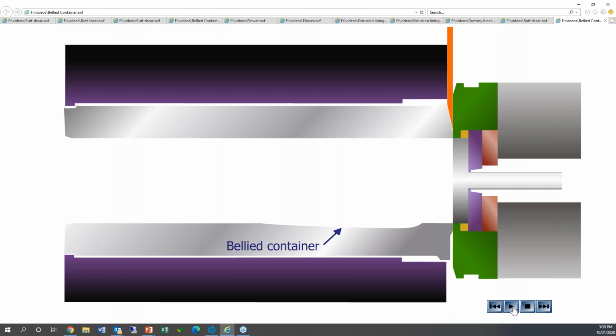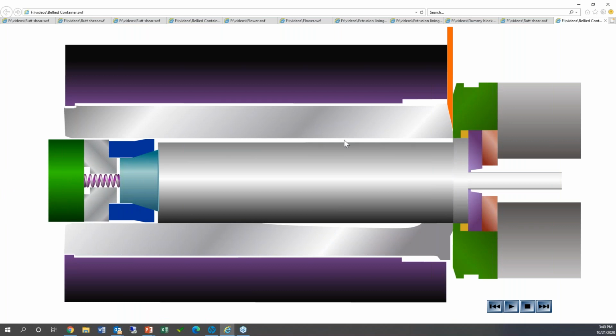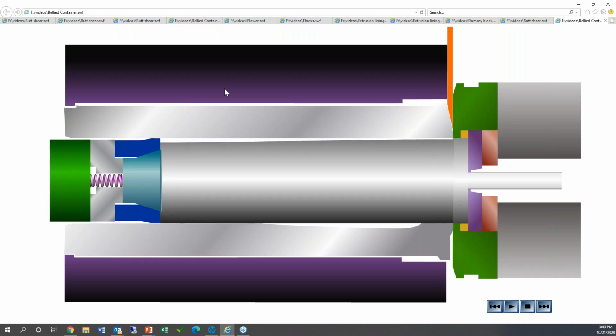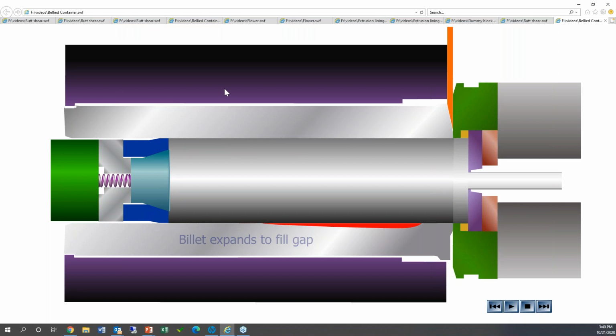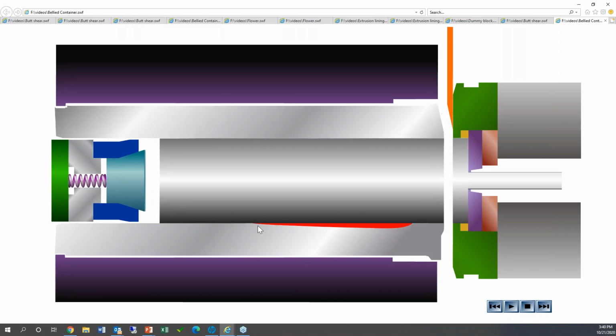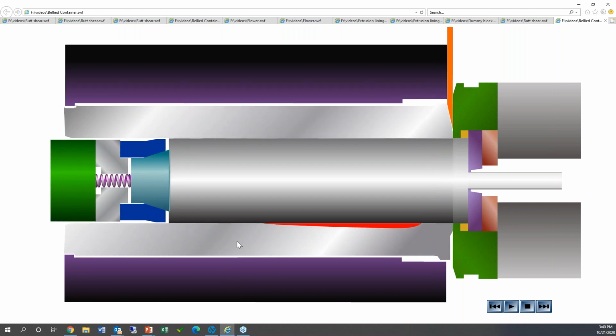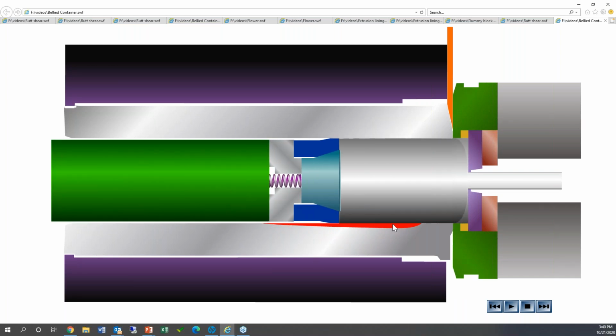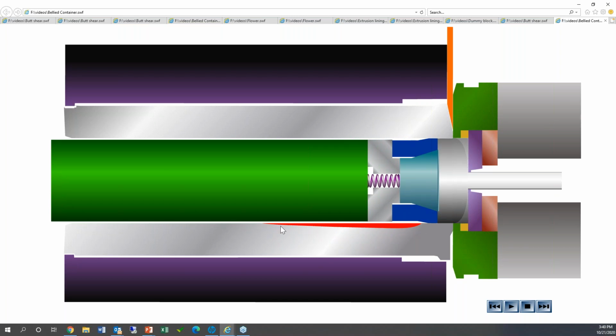Again, just a little video as a visual to what's happening when we have a softer container. That container soft and bellied, every billet, and I'm sure Richard's going to cover it, has an inverse segregation zone, which is basically like a bark to the aluminum. That inverse segregation zone gets loaded into this area that's bellied out onto the container. If you're only ever going to push one billet, then you're cool. It's all good in the hood. But if you're going to continue to load billet in here, you're going to continue to compile inverse segregation zone from the billet into this bellied area.